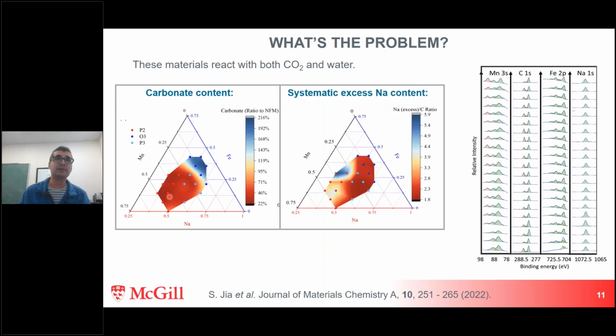And then you look at sodium. There was too much sodium in these samples based on the stoichiometry. And there was also too much for just being carbonate. The sodium to carbon ratio was 2 where we had this blue region. So where it reacts with carbon dioxide, we had sodium carbonate only. Elsewhere, we had another sodium byproduct. And it's basically sodium hydroxide, is the short version of this story.